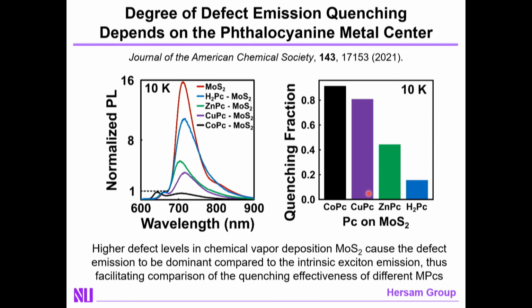Now, if you look at this as a function of the phthalocyanine metal center, again, you see a clear trend occurring here, where the degree of quenching of the defect peaks will depend upon the metal center that's present in your phthalocyanine. I note that in these experiments, we utilize chemical vapor deposited moly disulfide. This material is relatively defect laden, and as a result, the defect peak is actually the dominant peak. This small peak over here is the exciton peak. These are simply coming from the defects present in the material, and therefore it's much easier to observe the effect of the metal center in the phthalocyanine in terms of quenching of that defect peak.